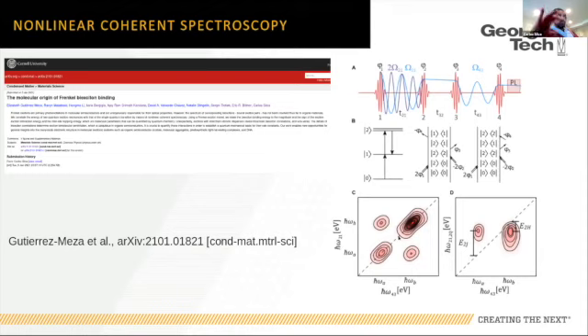But if I do a two-quantum experiment, where I'm measuring a correlation now of my two-quantum excitation with a one-quantum excitation, so now I have two transitions, XA and XB at the same energies here, but for the two-quantum correlation, I need to see if I see a peak that is above or below the rest of this two-quantum diagonal. If I'm at the two-quantum diagonal, this means that the two-quantum energy is twice the one-quantum energy. I just have two excitons and no interaction. There's no additional energy associated with the fact that I have two excitons.